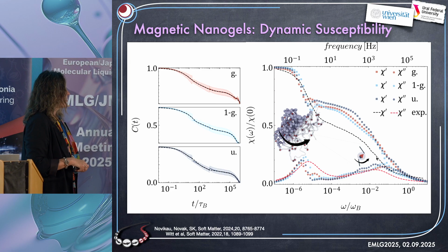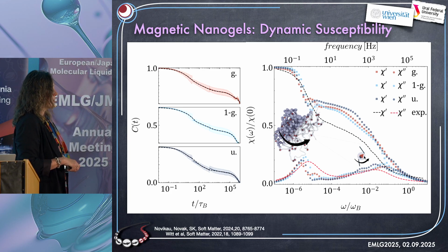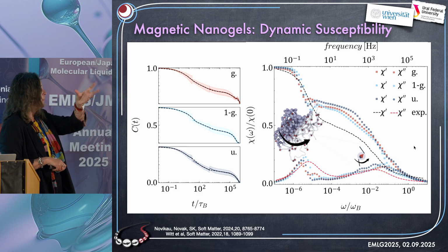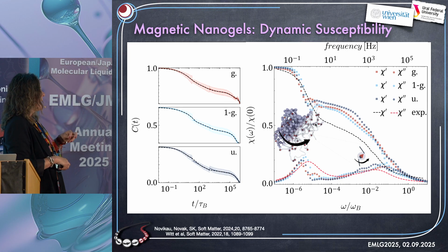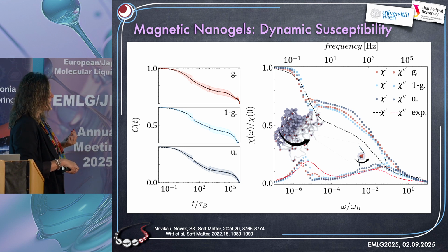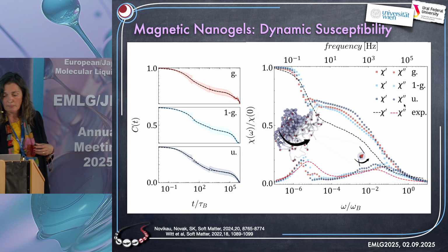So you can see two things. You can see that the eigenfrequency of rotation is very similar. It's a very similar effect, like if particles are clustered. So the frequency is very high. It's a very, very fast vibration inside the gel. And the oscillation of the gel is very slow. So you again have a very clear split that can actually be tuned mildly by the crosslinker distribution, but clearly only very mildly.